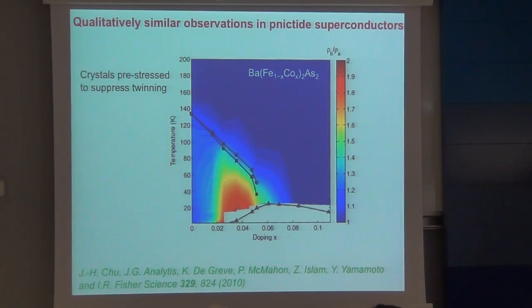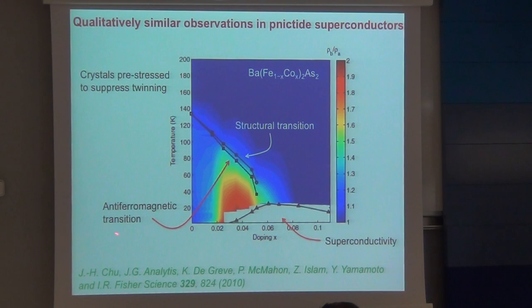I think the plot thickened even further and things became even more interesting when the pnictides were discovered and people began to look at the pnictide phase diagram in more detail. This, I think, has been led by Ian Fisher's group at Stanford. And here you have rather similar kind of phase diagram to the cuprates in many ways. You have superconductivity with a tantalizingly high critical temperature. Then you have a structural transition. Then you have an antiferromagnetic transition, so you have structural order, then you have spin order.